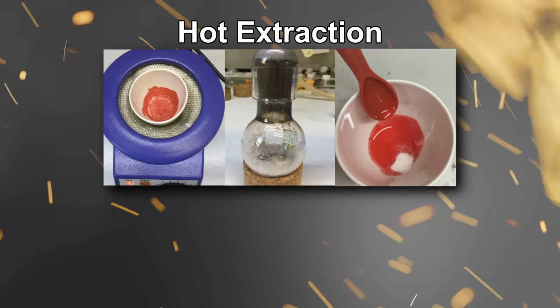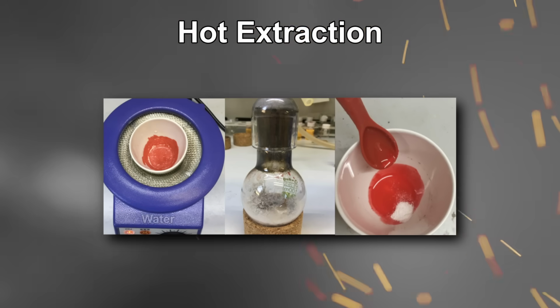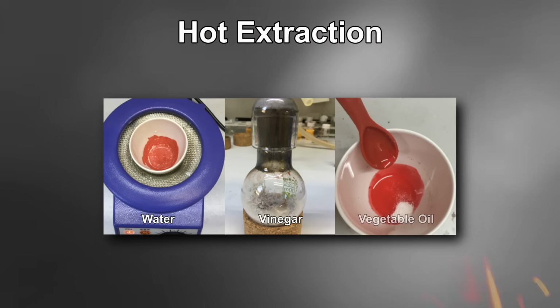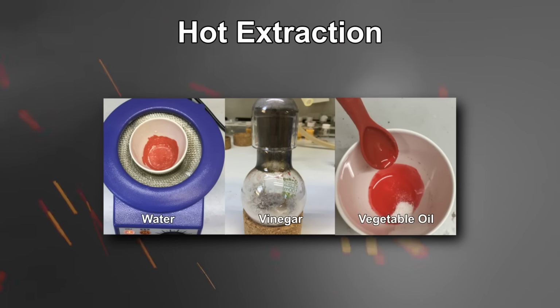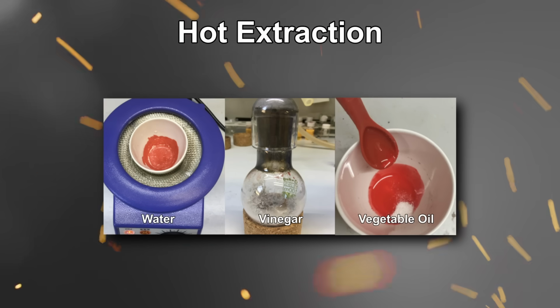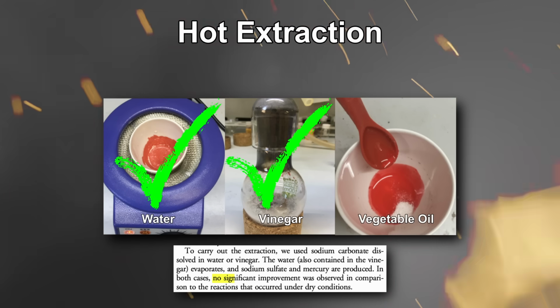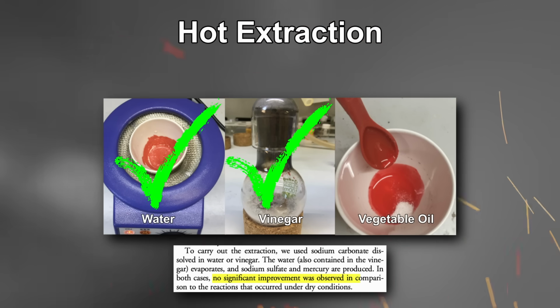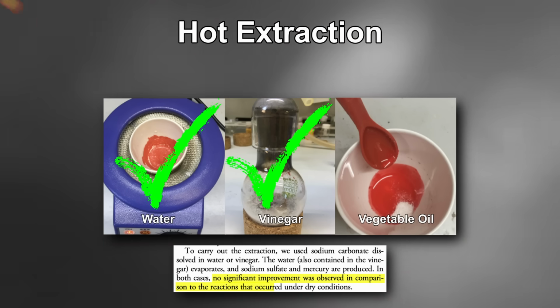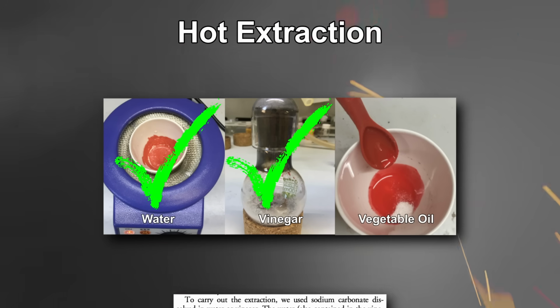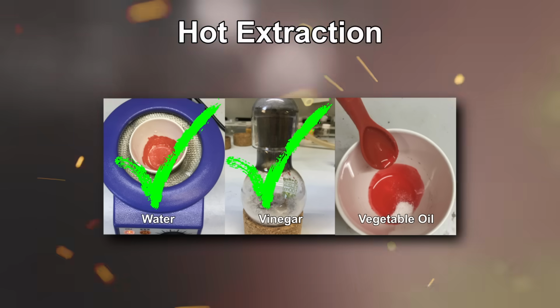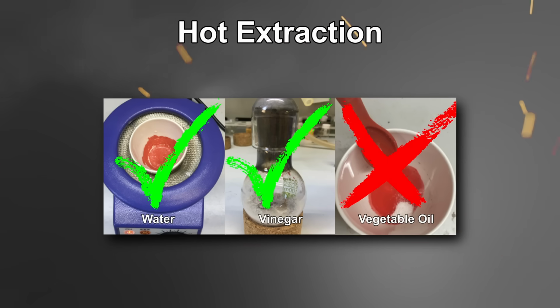They made up solutions of sodium carbonate dissolved in water, vinegar, and vegetable oil, and tried heating mercury sulfide in each one. For the first two solutions, although mercury was produced, no significant improvement was observed in comparison to the reactions that occurred under dry conditions. For the third solution, they couldn't manage to produce mercury at all.